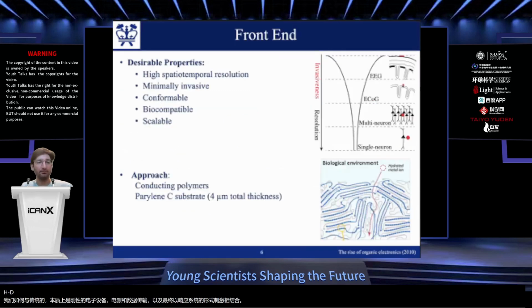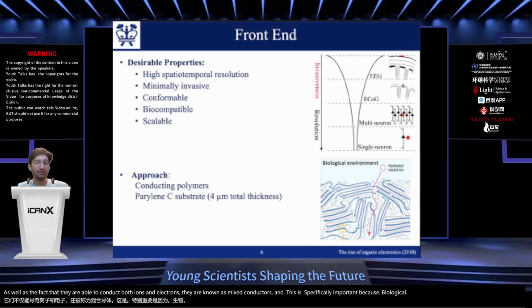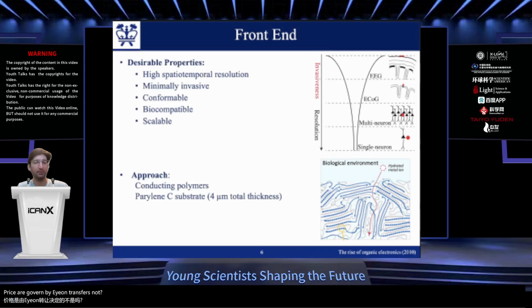Let's start. From the front end, we've always been inspired by organic electronics and organic materials, specifically because of their biocompatibility, as well as the fact that they are able to conduct both ions and electrons. They are known as mixed conductors. And this is specifically important because biological processes are governed by ion transfers, not electrons and holes. By improving this interface between the abiotic and biotic junction, we can potentially break this known trade-off between resolution versus invasiveness. We wanted to record more data, higher spatiotemporal signals, while minimizing the invasiveness.